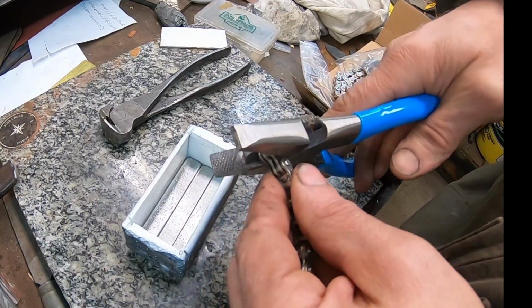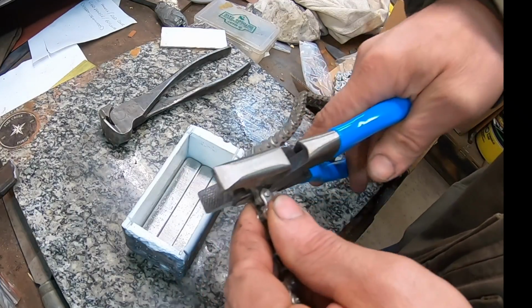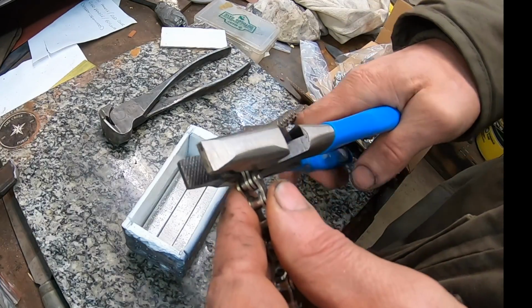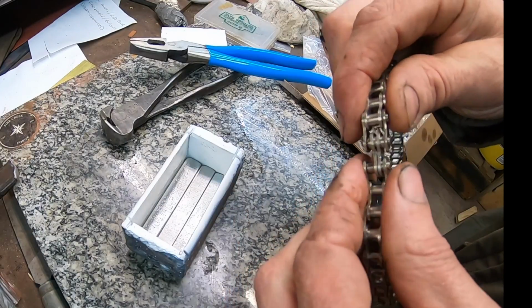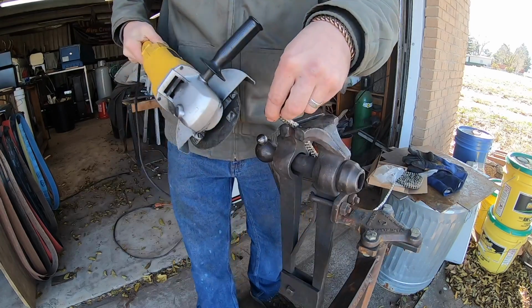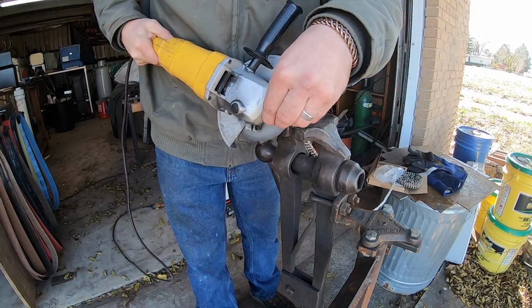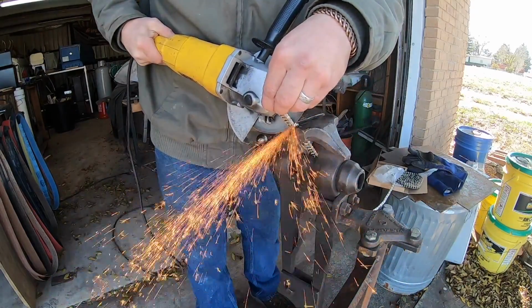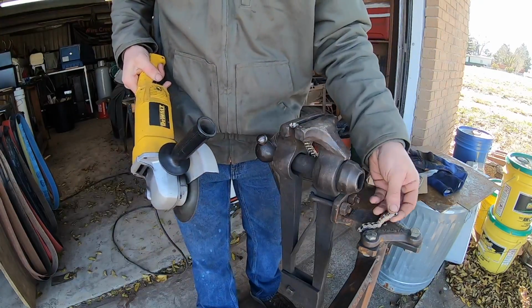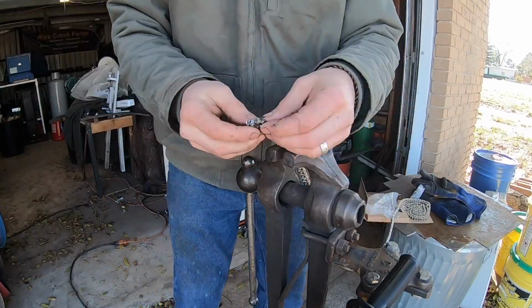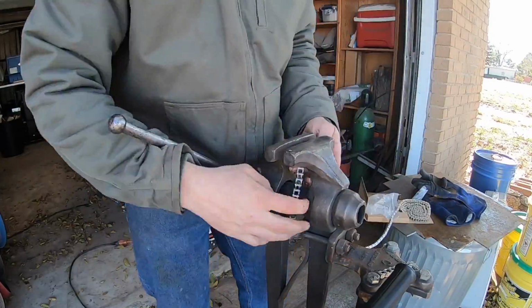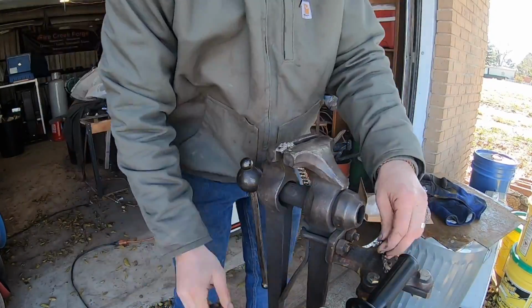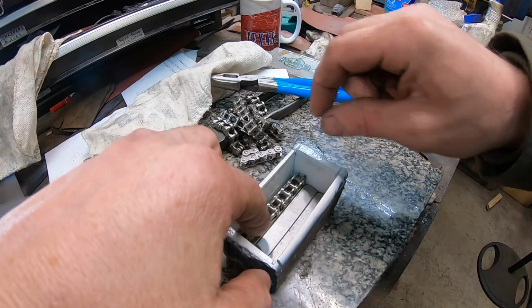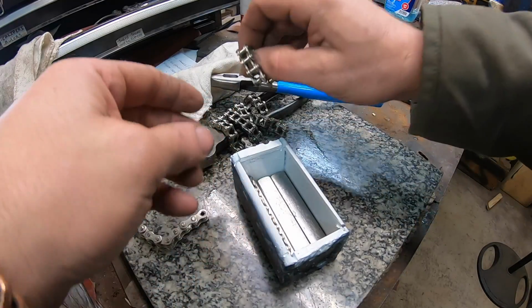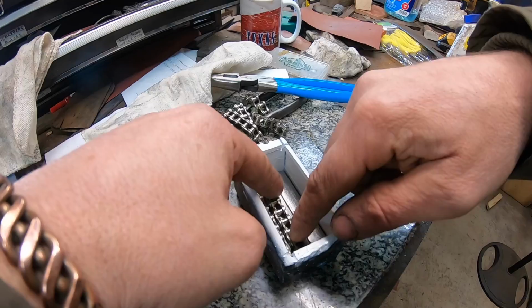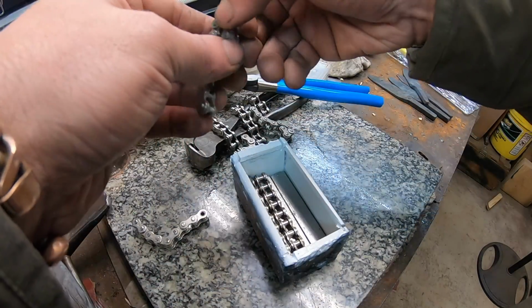basically bicycle chain, but it is nickel plated, which is going to provide a good contrasting pattern in the finished blade. Now you can see I can't cut through it with these nippers, and that is indicating that it's hardened steel, so it has to have at least 0.3-0.4% carbon, and probably around 0.5-0.6. I'm not sure, and that's why I'm not using it for the edge of the blade. But it is definitely hardenable steel, and it's going to have some good characteristics for the body of the blade, and it'll make a cool pattern for us, I hope.